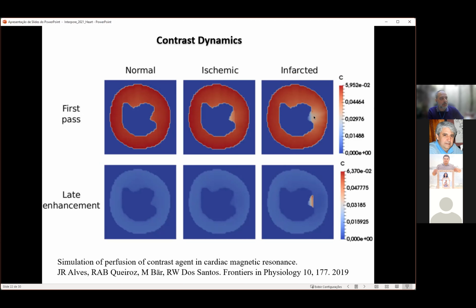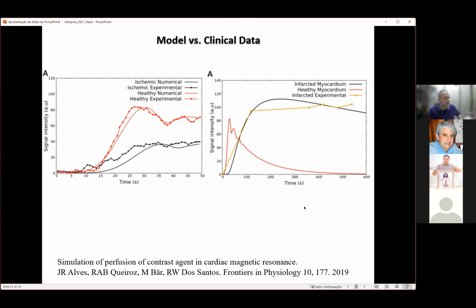And in the case of infarct, we have a very severe obstruction here. So you already see again some problems in the perfusion. And when you do again the exam, you see the contrast was trapped in this place, which has a damage, fibrosis, infarct. And we could calibrate the model using clinical data, so we could replicate pretty well what was happening.